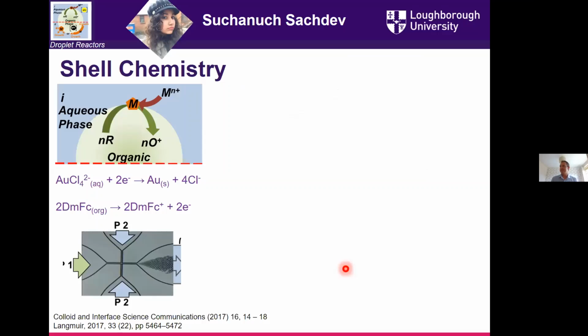I'd managed to convince her that this was a good project, that this would be a really cool thing to do. And the starting point was to look at some gold chemistry, and just to look at what we call shell chemistry. So we're not going to fill anything in the middle of the organic droplet now. We're going to have some reductant in the organic phase. We'll have metal ions on the outside, in this case gold, and we'll let that reaction take place.